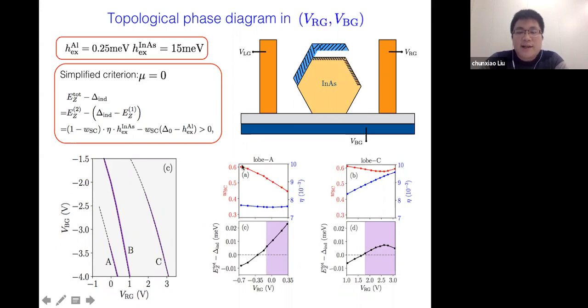But here is a little trade-off you need to pay attention to. For this hybridization, although a smaller value will help to realize topological superconductor, in the end, the topological gap is proportional to the induced superconducting gap. So you don't want to tune it to be too small, and you want it to be a moderately small value, say between 0.5 to 0.4, so that it is in the topological phase, and at the same time the topological gap is not too small.